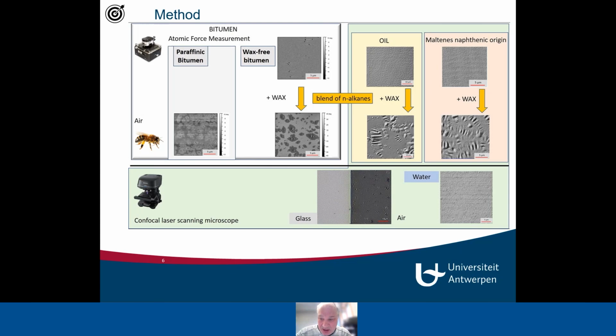So we had two techniques, and we started with paraffinic bitumen because we knew there were some bees at the surface there. We could observe them. We also knew that with wax-free bitumen we don't see any bee structures at the surface. By adding these waxes, we could generate these wrinkling effects, which occur in these bees, and we could observe them both in AFM and in confocal microscopy.